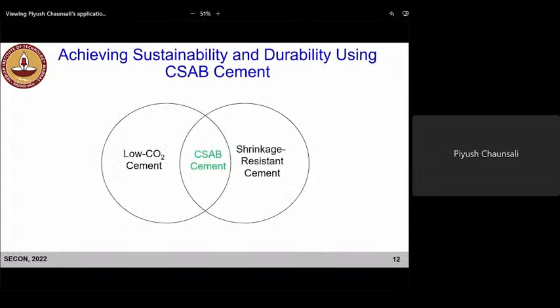So CSAB cement offers you both. It is a low CO2 binder because less limestone is used to manufacture CSAB cement. CSAB cement manufacturing requires a rotary kiln temperature of around 1250 degrees Celsius. So you have a 200 degrees Celsius difference. Also, this CSAB cement clinker is more porous than Portland cement clinker. So the grinding energy requirement to make this cement is less than the requirement for Portland cement clinker. So there are so many advantages. That's why we said low CO2 cement, and we have seen that we can also leverage this expansion, which can be achieved for making shrinkage resistant cement. So both low CO2 cement, so sustainability, and durability, right? Both can be addressed through the use of CSAB cement.